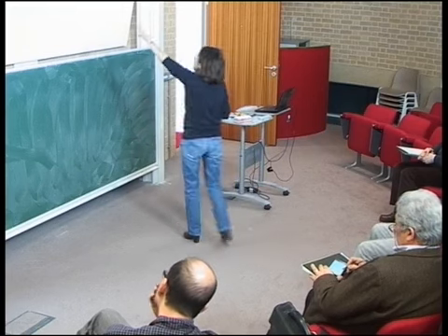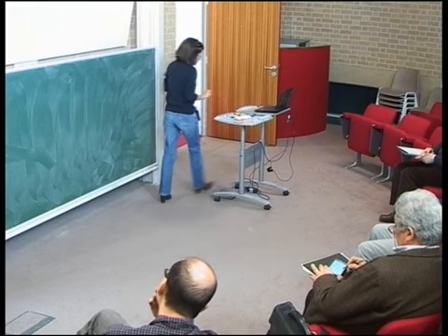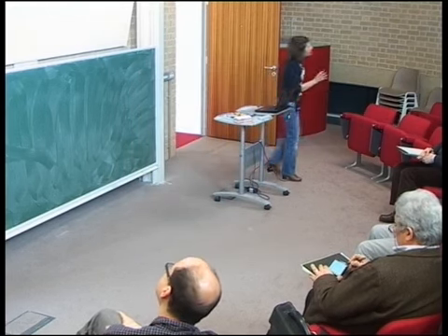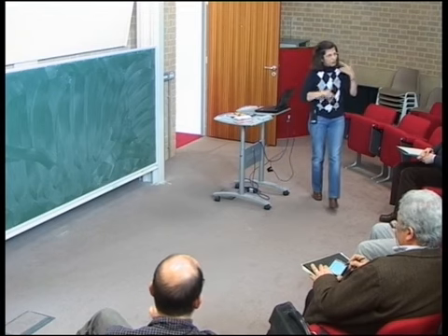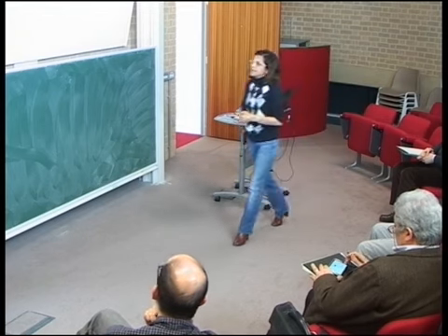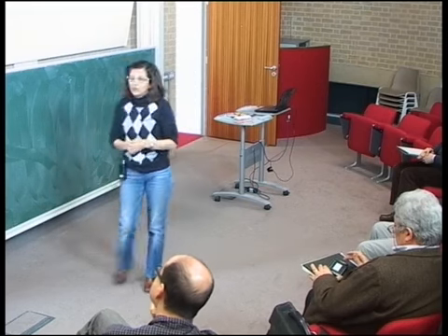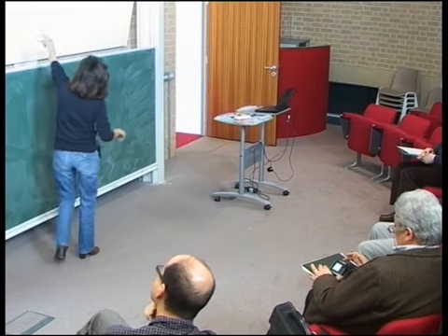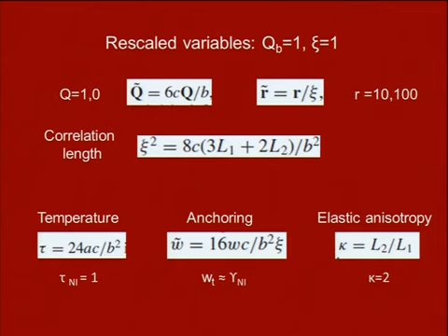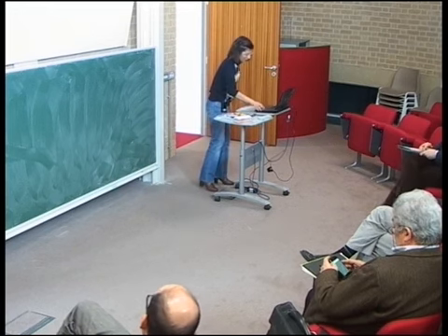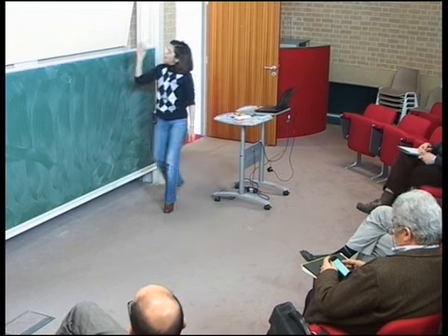And anchoring is the strength of my surface potential, but where these transitions occur, through some dynamic arguments, but also through some detailed calculations, you can show that this anchoring is of the order of the free interfacial tension. Okay, so I tried to look at some data, and even asked Tim for 5CB for the surface tension of the nematic isotropic interface, and I had to estimate it.